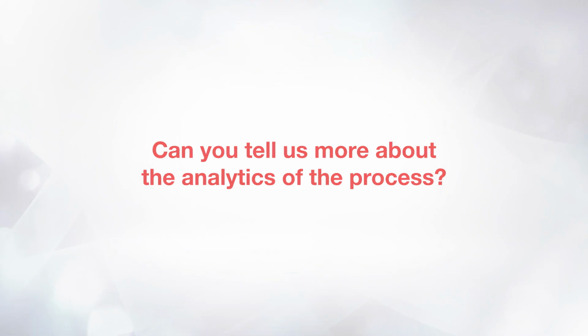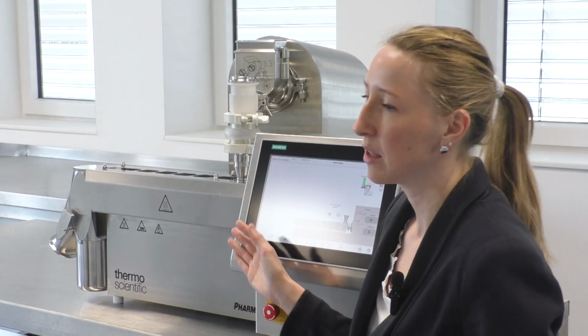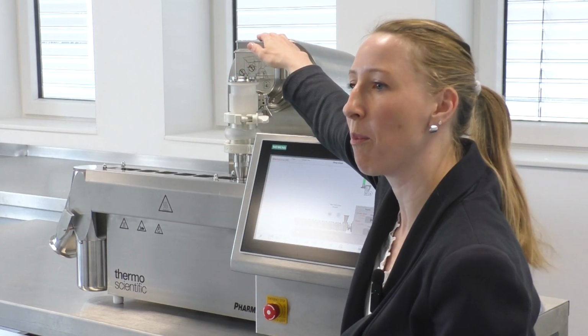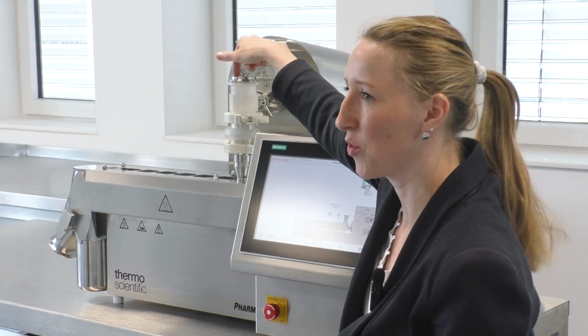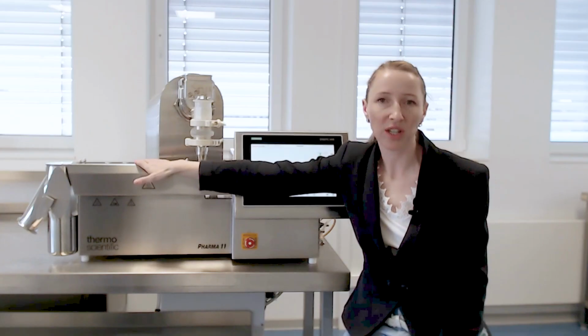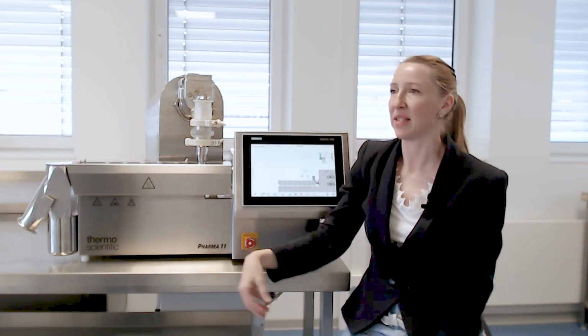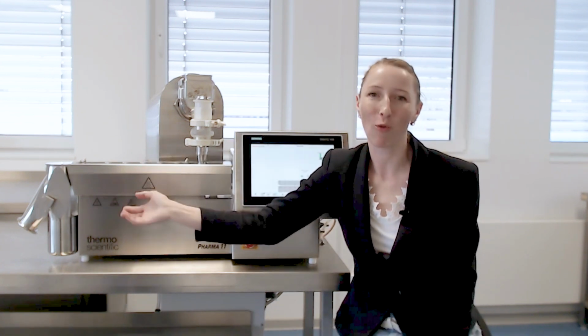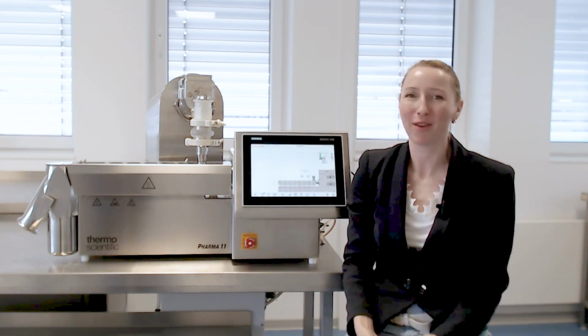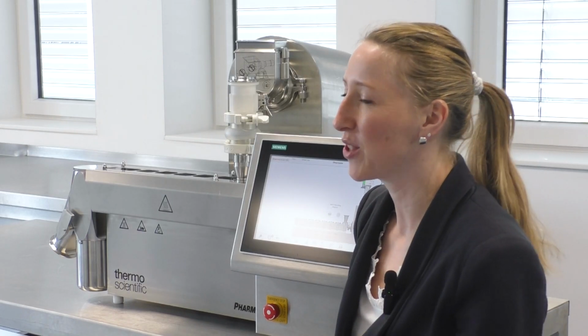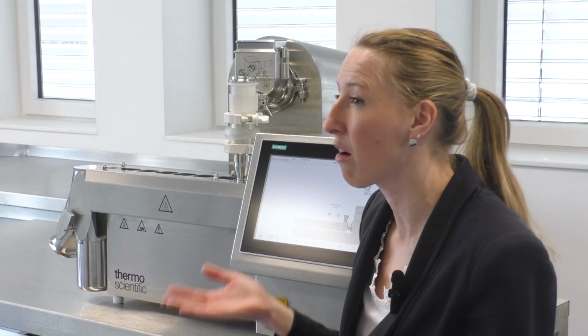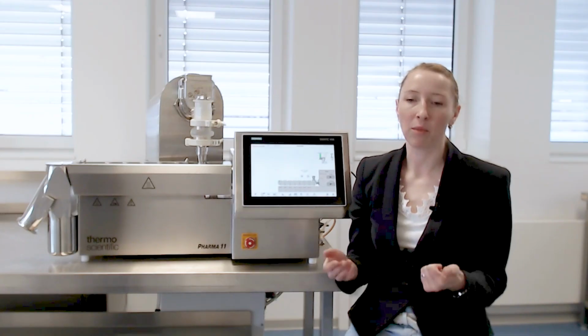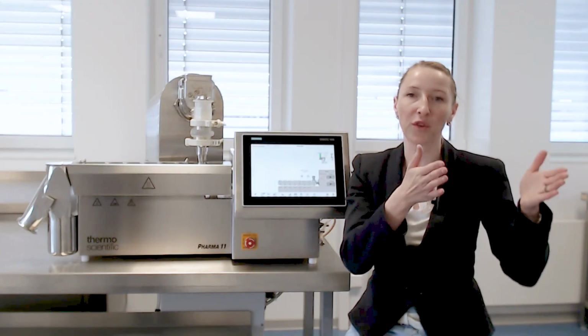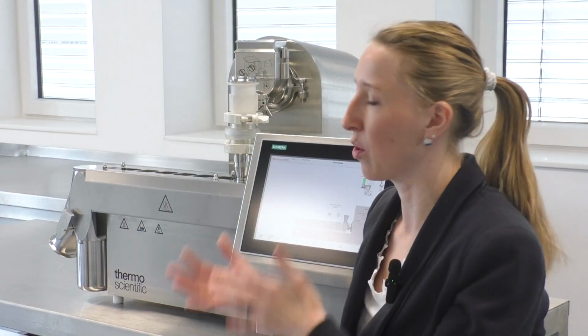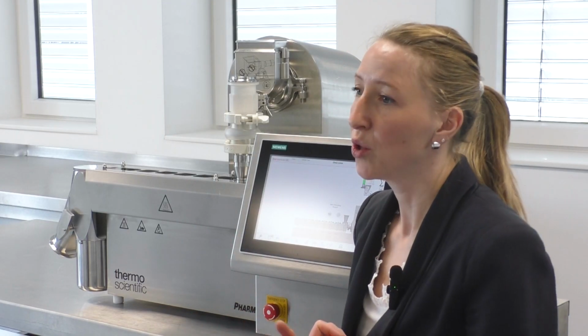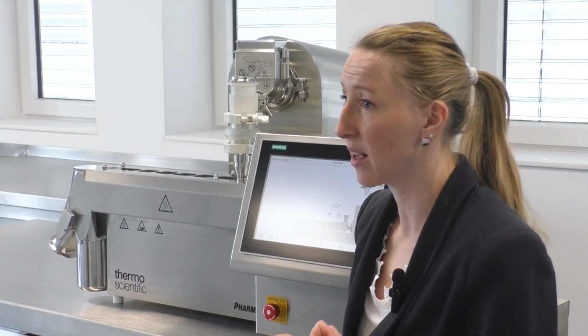Yes, the analytics. That's a good point, because when you run the process, you have white powder, so the powder blend that's going into the extruder in the main feed. The extruder in twin screw granulation mode is processing the material, and then you have white powder coming out of the barrel. So you basically don't see what is happening. So is it working or not working? What we wanted to see is the difference between the crystalline state and the amorphous state, and that's nicely possible using DSC, so differential scanning calorimetry.